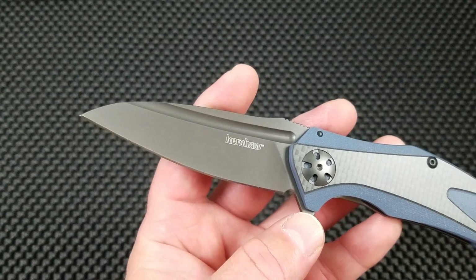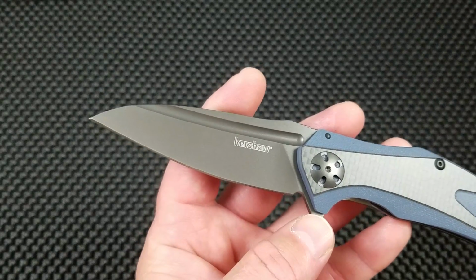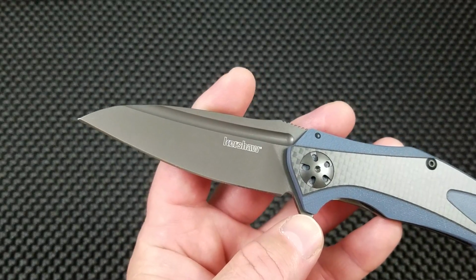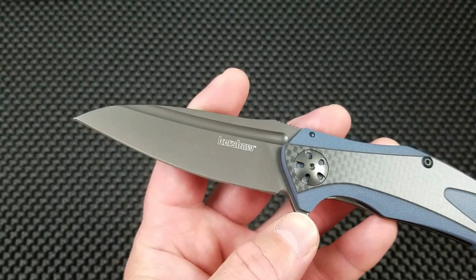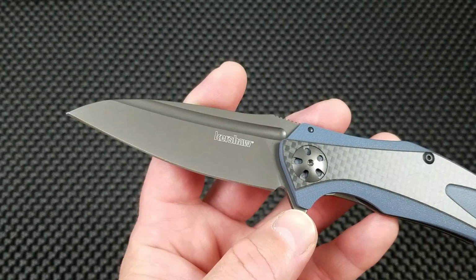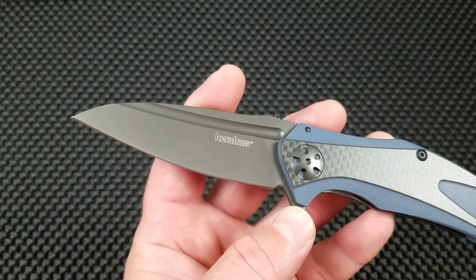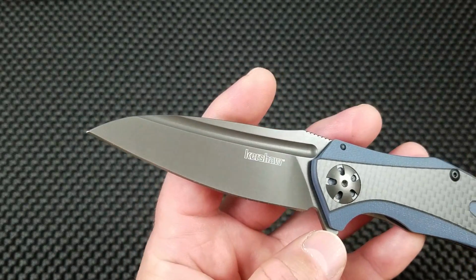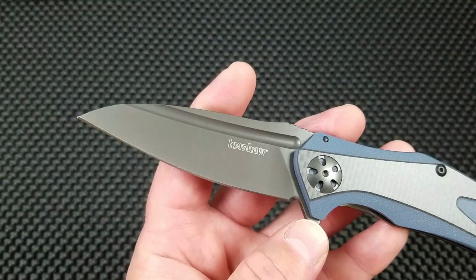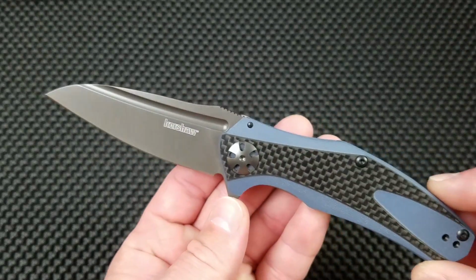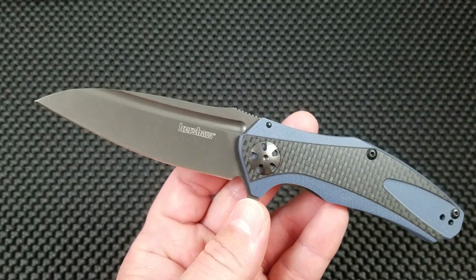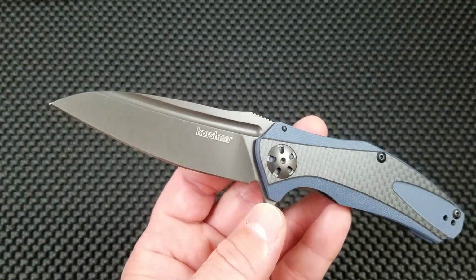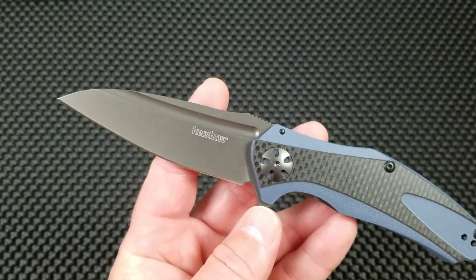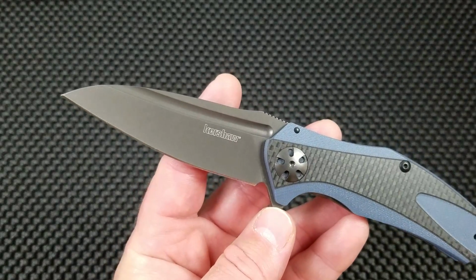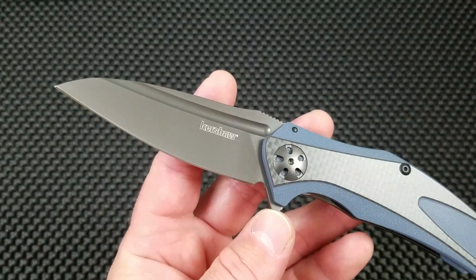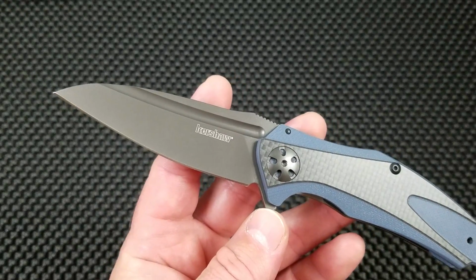You're looking at a carbon content of 0.7 to 0.8, a chromium content of 13% to 14.5%, and it is a vanadium alloyed stainless steel with 0.1 to 0.25% of vanadium. You'll typically see it Rockwell in the 56 to 59 range, and what you get out of this steel is decent edge retention. It's easy to resharpen. It'll take a polished edge if you like that. The toughness and impact resistance is fairly good. This steel will tend to roll before it will chip or crack.